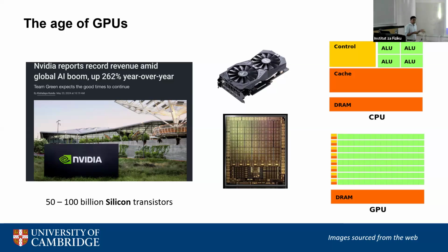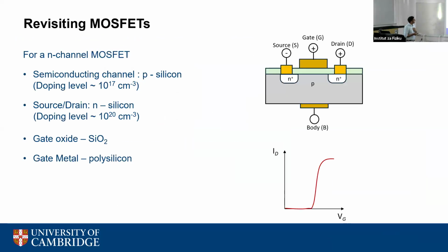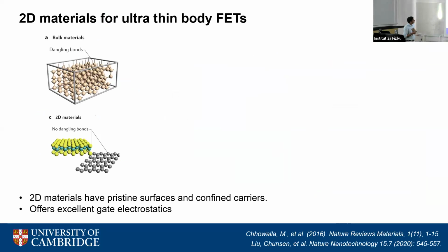But as we are getting smaller and smaller, we are having problems because as we reduce the size of the transistor, we are also making them thinner. And as you make them thinner, surface effects start to play a huge role. For example, in 3D materials, you have dangling bonds. If you make them really thin, these dangling bonds often act as scattering centers and affect the mobility of carriers moving through this channel.